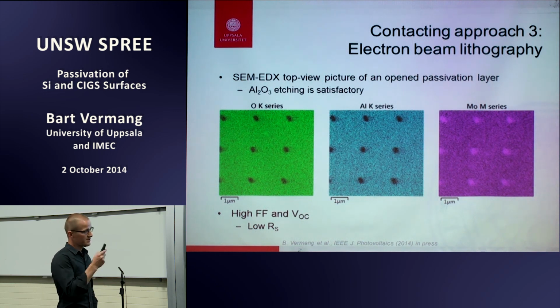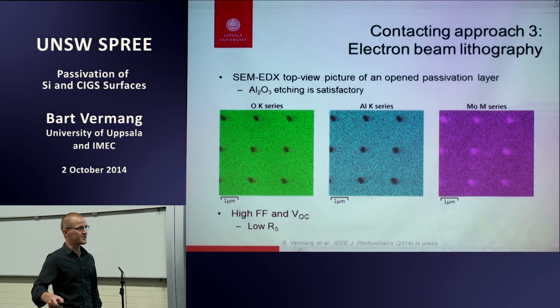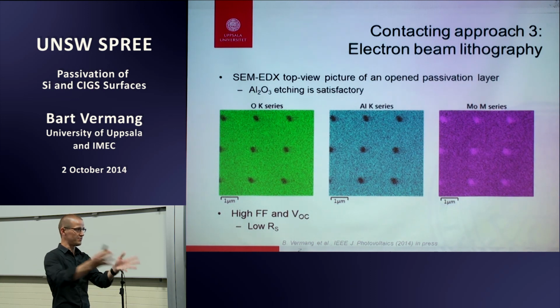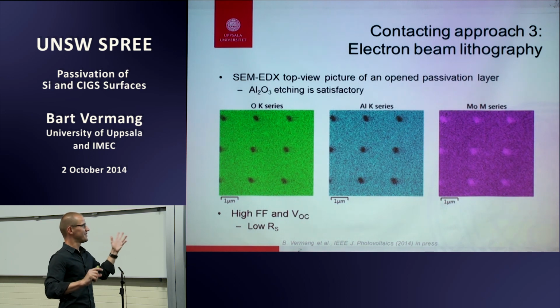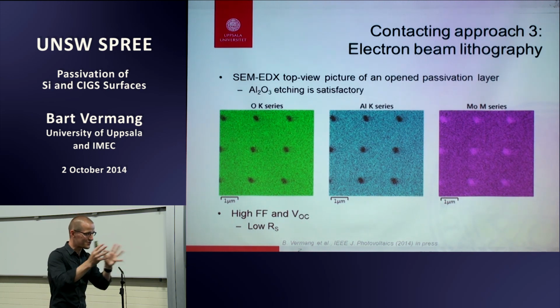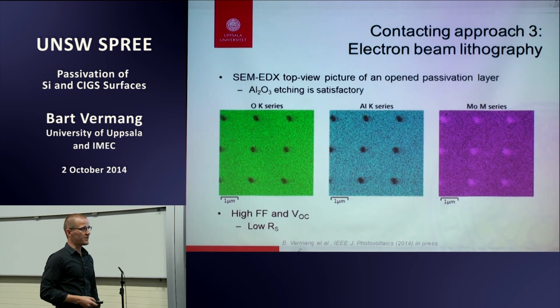We also have been measuring the sodium content in CIGS layers for full layers of aluminum oxide. Because in the beginning, getting the first SEM and TEM pictures, having the passivation layer and the openings, that was really like a breakthrough because we could prove this is the way the cell looks. And it was very difficult because of the very thin aluminum oxide layer in the beginning. So at that moment, I made complete devices without point contacts and very thick passivation layers, just to make pictures that I could show the passivation layer. And with those we have also been measuring where the sodium was and everything. And yes, it was a very good barrier layer for sodium.